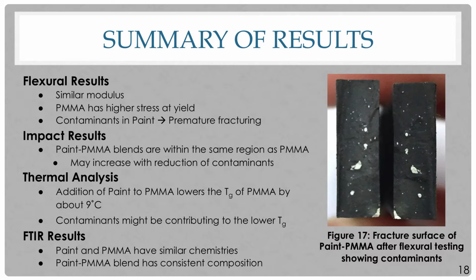to molding. From thermal analysis, we found that adding the paint into the PMMA lowered its glass transition temperature by about 9 degrees Celsius. And contaminants may also be a contributor to this lowering. Finally, from FTIR, we found that the paint and PMMA both have similar chemistries, which make them good for the blend. And the paint PMMA blend that we created has consistent composition.